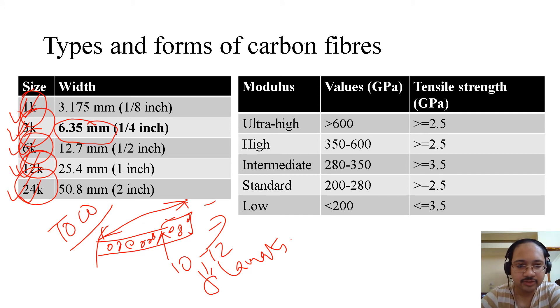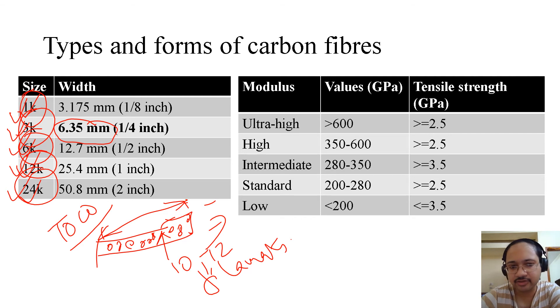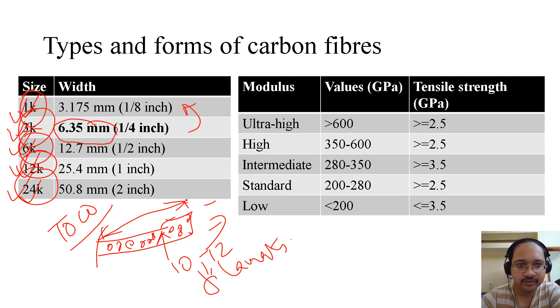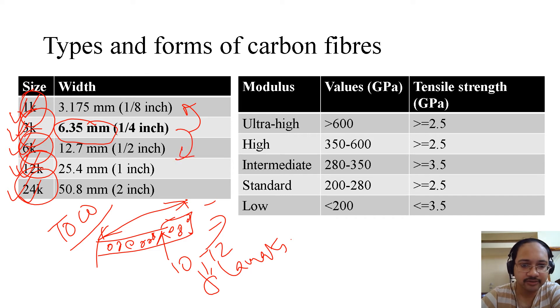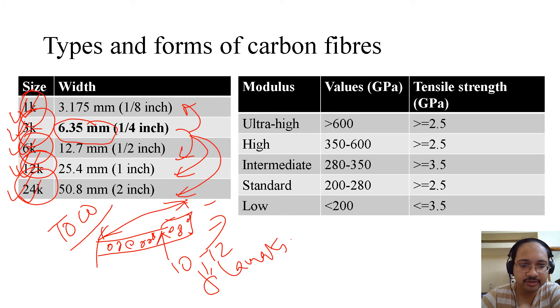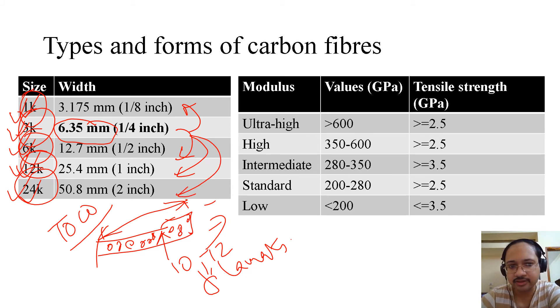To remember the widths: a 3K tow is quarter inch or 6.35 mm. If you halve it, you get 1K; if you double it, you get 6K; double again for 12K; and double once more for 24K. So by remembering just one value, you can work out the widths of all the other tow sizes.